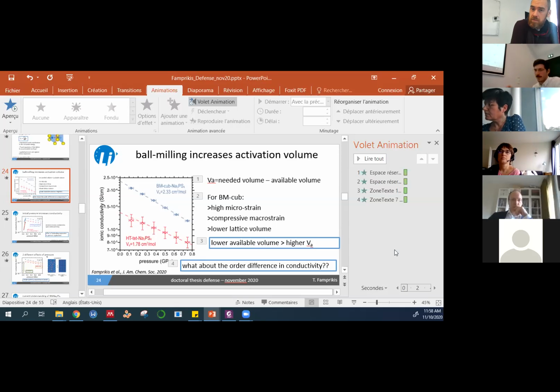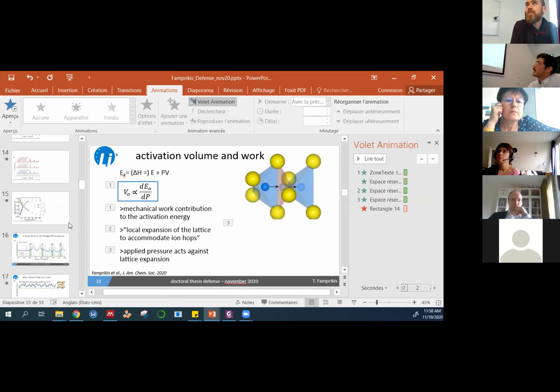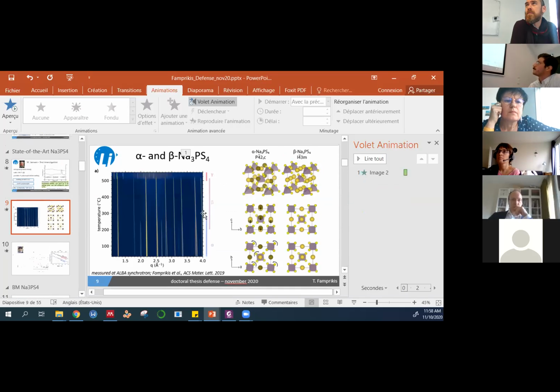If you look at the structure of Na3PS4, there is, at least intuitively, much less room to play with. If you consider it as I do, as made up by a body-centered cubic arrangement of the PS4s, then you can see that all of the 6-coordinated sites are actually filled here. There is no real room to put extra sodium. You could then make the argument that maybe I have less sodium. Yeah, but then you would need more phosphorus to make up for the plus charge. Where do you put the phosphorus? Yeah, or less sulfide, as you mentioned. Less sulfur, yeah. As you propose in your NMR, I know it was a hypothesis, but it could be also. Yeah, definitely.